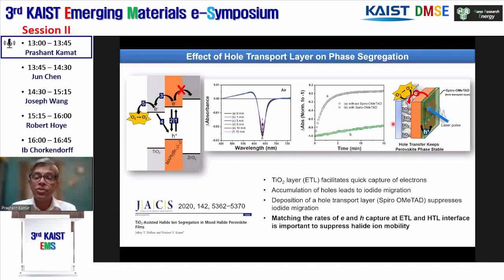So we also did another experiment. What happens if you put a hole transport layer, like spiro-OMeTAD, on the TiO2 layer here, and then the electrons and holes are now being scavenged, and there is no accumulation in the perovskite film. So what we see when you see this bleach, again, the same experiment as before, if you don't have the spiro-OMeTAD, the mixed halide phase recovers very quickly to generate the iodide- and bromide-rich phases. Whereas if you put spiro-OMeTAD, we don't see that kind of behavior. So it again points out that the hole accumulation is the one that is resulting in the phase segregation, and it doesn't happen if you have a hole transport layer.